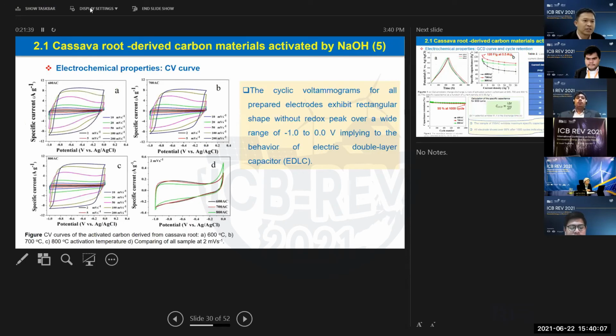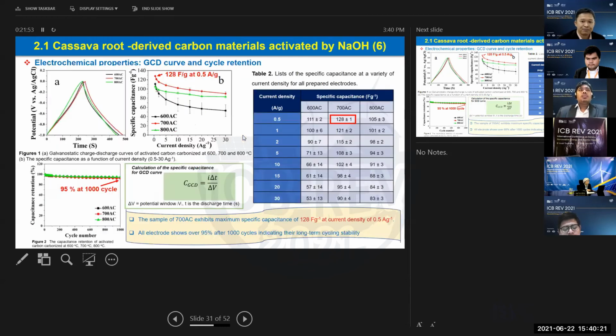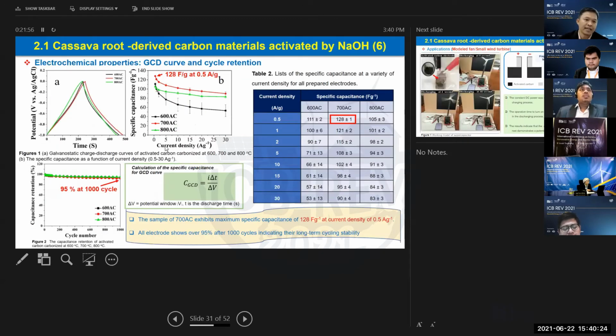And for the electrochemical properties, we also do the same measurement. We use the CV and also the GCD techniques to evaluate the electrochemical properties. And from this, we can calculate the specific capacitance. The highest specific capacitance is observed on the sample prepared at 700 degrees Celsius, which has a specific capacitance of about 128 farad per gram at 0.5 ampere per gram. And as you can see from this figure, 700 degrees Celsius is the best condition.